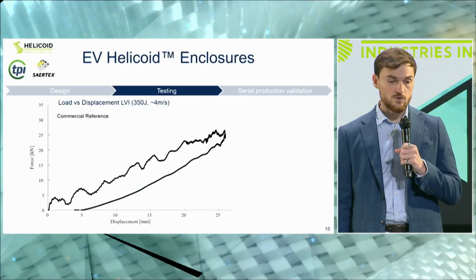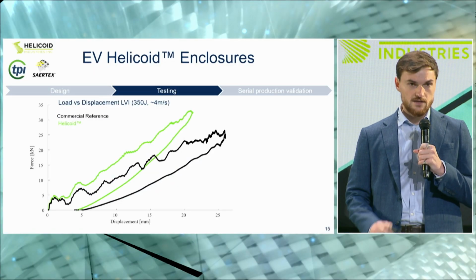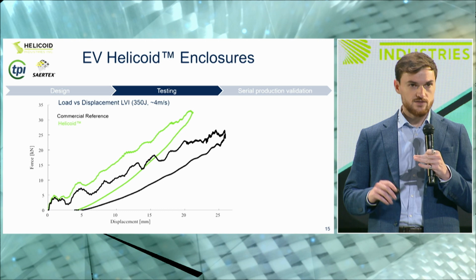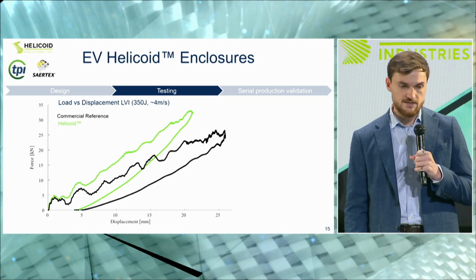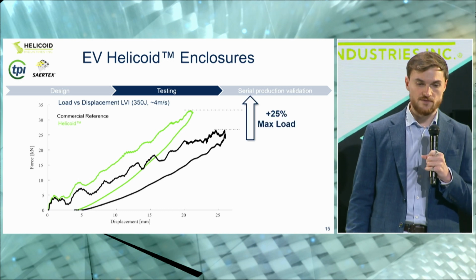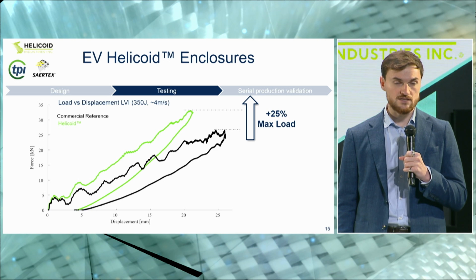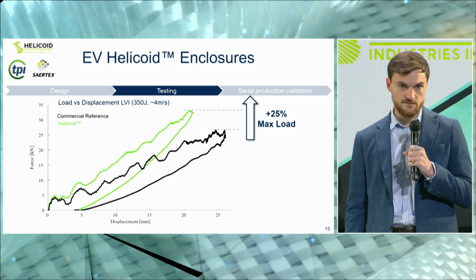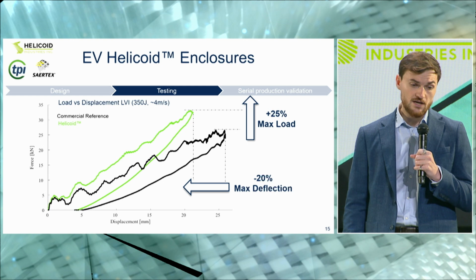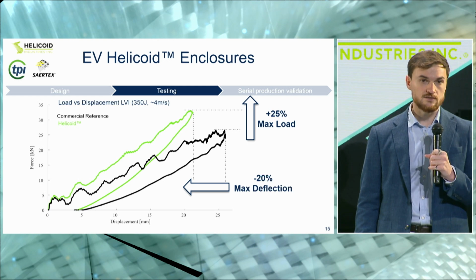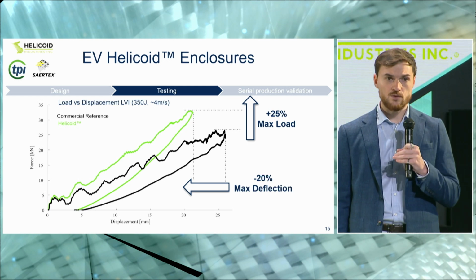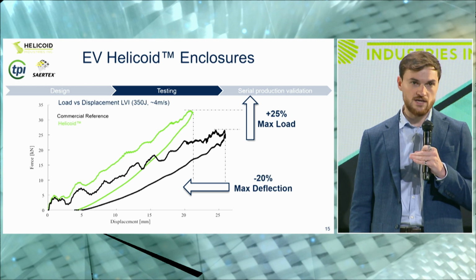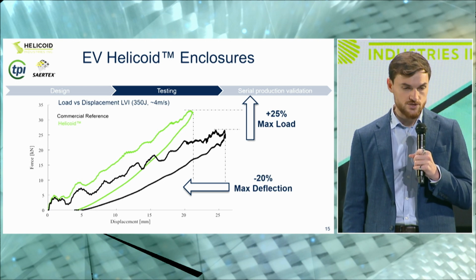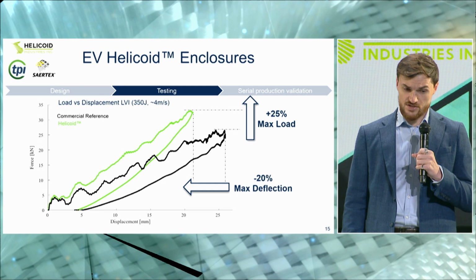But if you overlay the Helicoid design, here we were targeting same weight, just improved performance. You can see how our design was capable of achieving a 25% increase in load-bearing capability of the underbody protection, and more importantly, a 20% decrease in deflection. Again, we are using same fiber, same resin, just an optimized architecture. This is not the whole story.